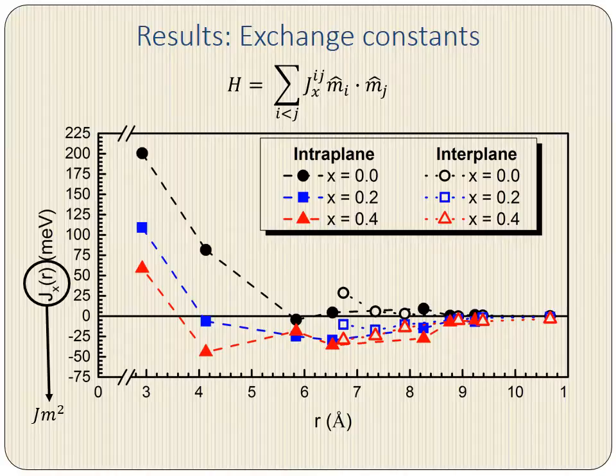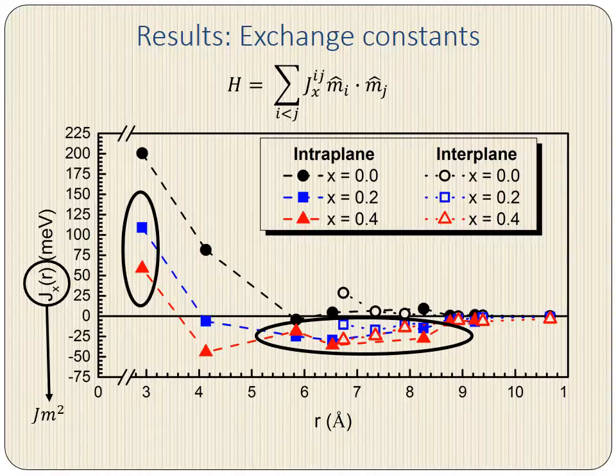In this plot, the exchange constants are shown as a function of distance for intraplanar neighbors and interplanar neighbors for 3 different hole doping levels, which are all indicated in the legend. We note that the intraplanar results and interplanar results both lie on the same rough universal curve. Now for no hole doping, we see that the interaction is antiferromagnetic and tapers off quickly with distance. When we do include hole doping, which is what we see for the red and blue symbols, we see that for further neighbors, a ferromagnetic interaction is activated, while for nearest neighbors, the coupling remains antiferromagnetic.